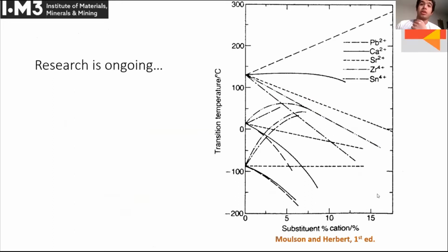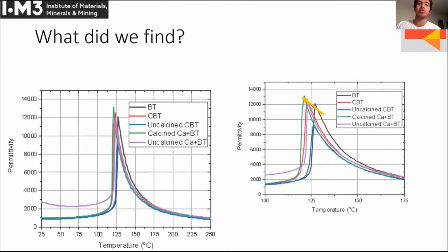So this is a plot that has quite a lot of information. I'll focus your attention towards the transition temperature of 125, which is what we were trying to work on, and we were interested in the calcium substitution — so looking at the solid line. As we can see, the more we add calcium, the transition temperature falls ever so slightly, which is what we saw with this plot essentially.